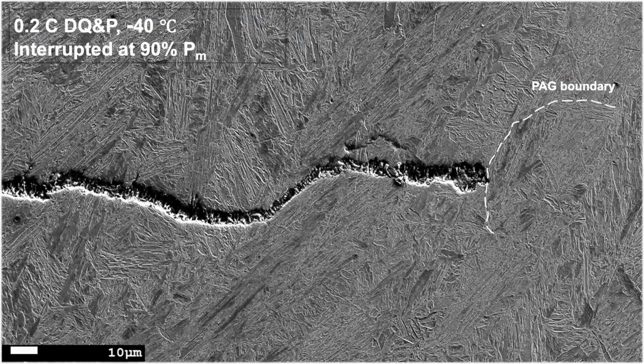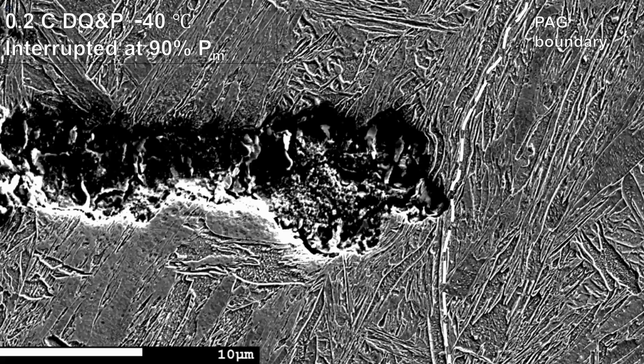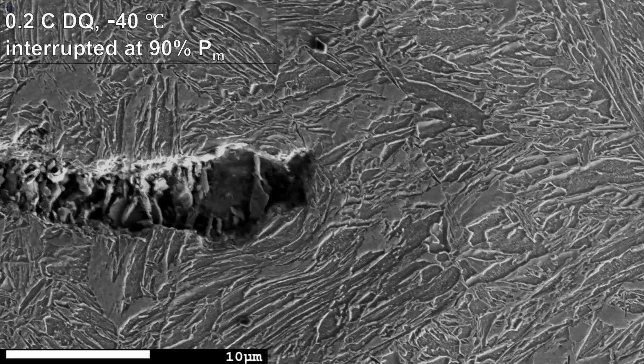And when we look at how these deform, on this direct quench and partition material, this was the case with interrupted testing. We can see on this individual case that it stopped at the prior austenite grain boundary. But if we look a bit further, we see that there's still a high level of local deformation on the crack front and around the crack front. So despite these strength levels, we have some local deformability. Also, if we take just this direct quench version without retained austenite, or at least close to the detection level, there's still lots of local plasticity playing. But what is limited is the extent to which it can dissipate the stresses through the deformation.